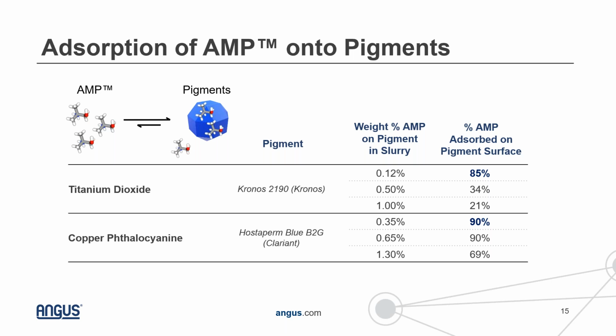In the case of titanium dioxide, what we did was prepare a slurry with the specified weight % of AMP on pigment. If you look at that first line, we're looking at 0.12% weight of AMP on pigment. Then we can characterize how much of that AMP is in solution and how much is on the particle surface. What we find is that in that case, 85% of the AMP is found on the particle surface and not in solution. As you increase the amount of AMP used in that pigment slurry, you see a general decrease in the amount of AMP adsorbed on the pigment surface.